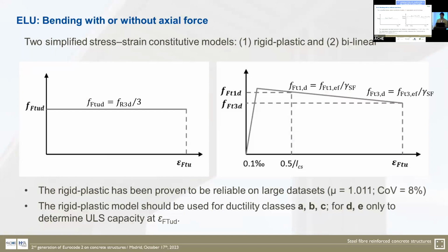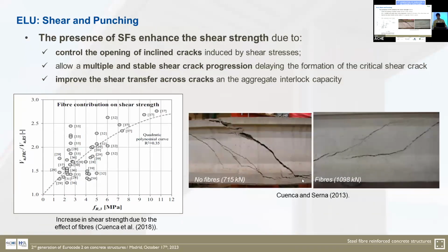For ultimate limit state, there are two constitutive equations proposed. One, rigid plastic, which is defined by the design value of FR3 divided by 3. This is the tensile residual strength. Or for more accuracy, we can go to a bilinear constitutive relationship. I must say here that with the database that we have, gathered in the background document, the accuracy using this constitutive model, compared with the flexural tensile test of beams, the average error is 1, and the coefficient of variation of this error is 8%. So very reliable models, although very simple.